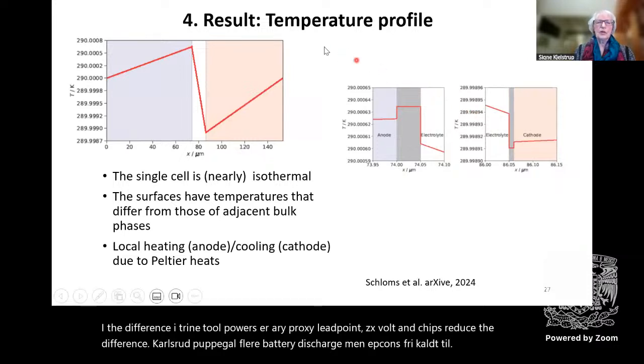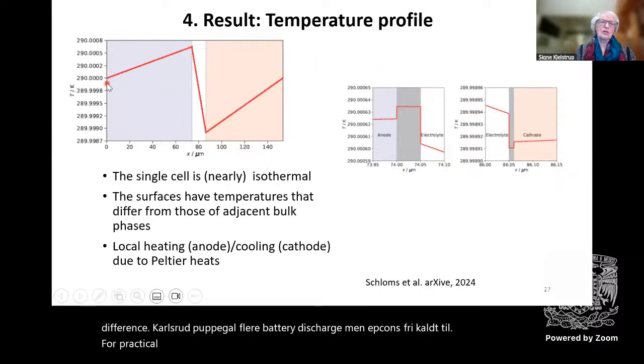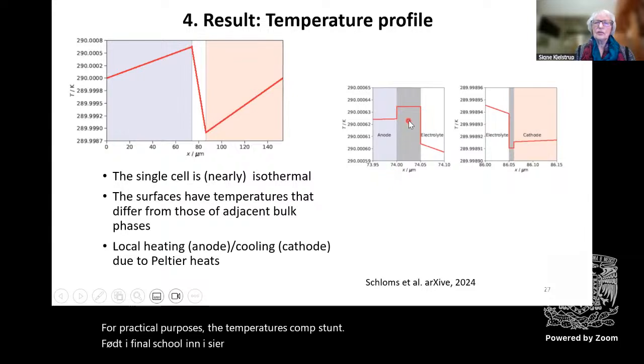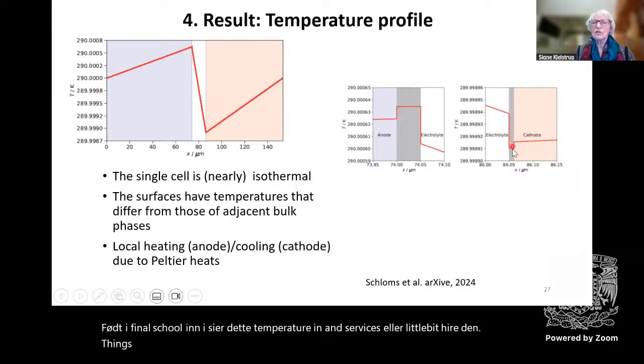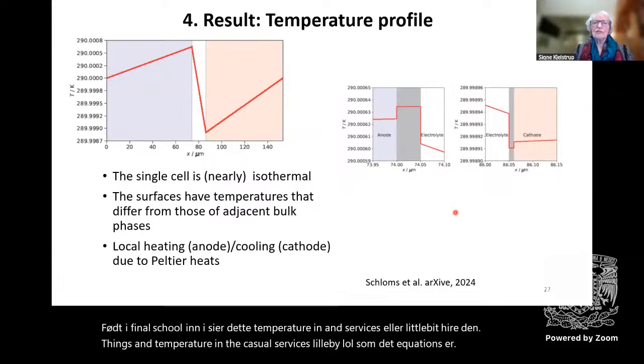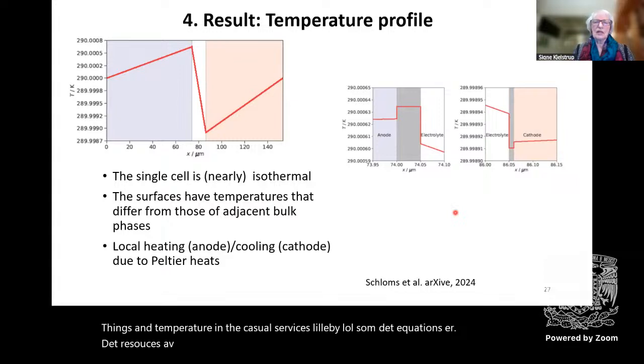For practical purposes, the temperature is constant. But if you now zoom in, you see that the temperature in the anode surface is a little bit higher than the surroundings, and the temperature in the cathode surface is a little bit lower. So the results are reflecting the equations that we have, that here was a warming effect and here was a cooling effect.